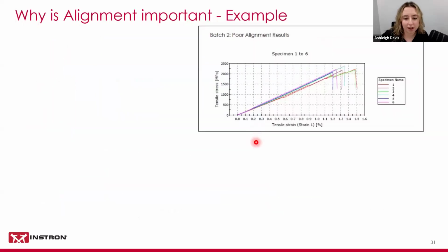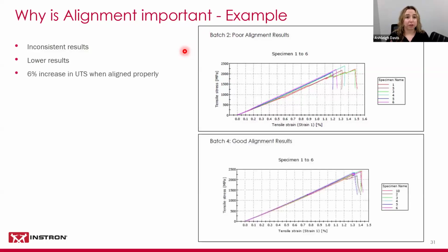We did some tests a couple years ago where we purposefully tested coupons in a misaligned load string. So here we had an instance where we had grips in the frame, but the grips were not aligned using any kind of secondary alignment feature. And there was bending moment occurring within the preloaded specimens at about 26% bending moment.